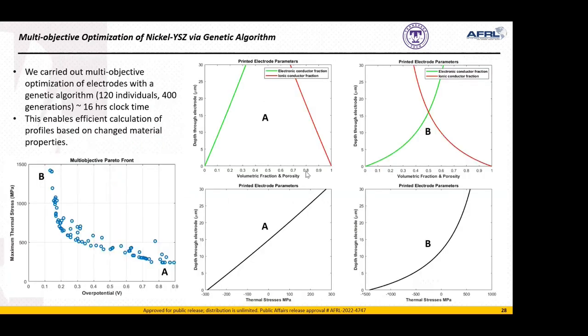Well, now what we did is we fed this boundary value problem with the electrochemistry and the thermal stresses into a genetic algorithm. And here we see the benefit of using a reduced order model such as this is that we can sort through thousands of individuals in less than a day. So someone can have a material combination that they are interested in for an electrode, and within a day or two, they can have a relevant answer of what the ideal compositional 3D printing profile would be for that electrode. Here we see the individual that performs the best as far as reducing the absolute thermal stress is individual A with a linear gradation. Individual B has the minimal polarization resistance.